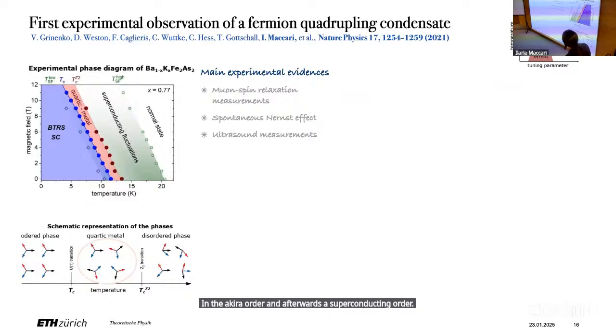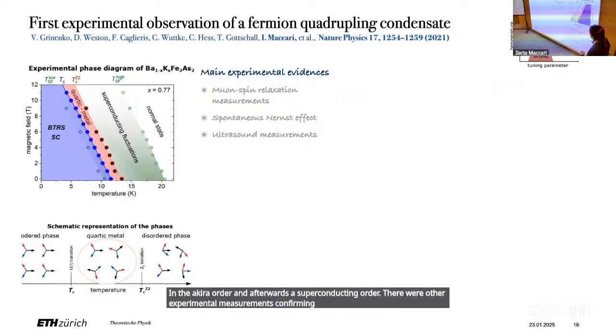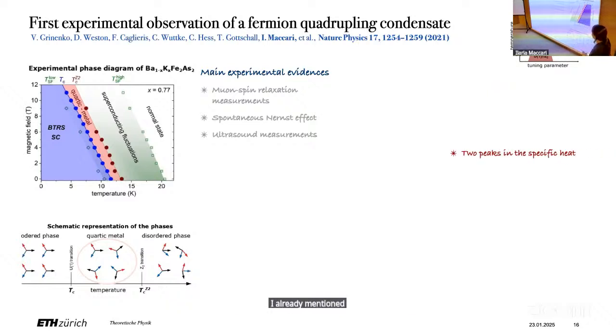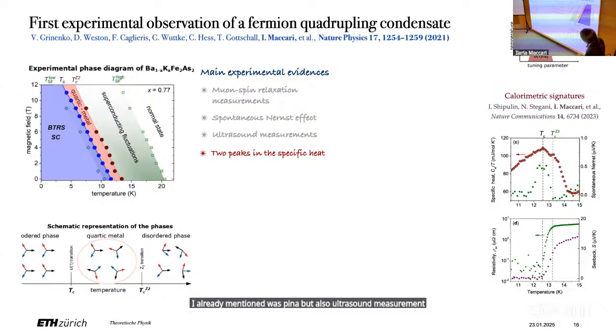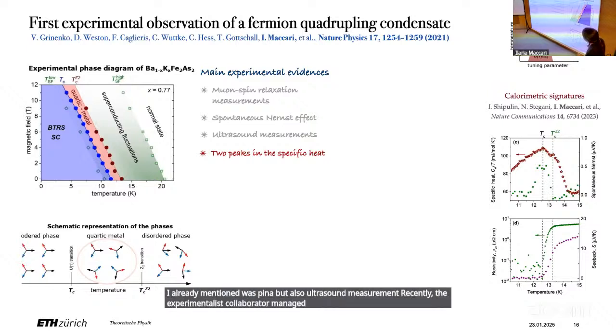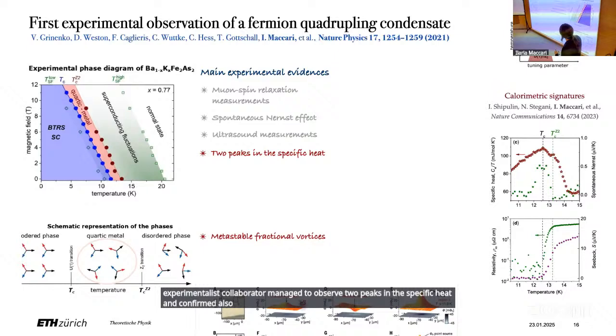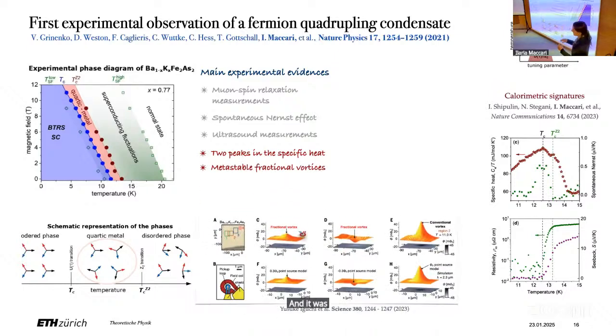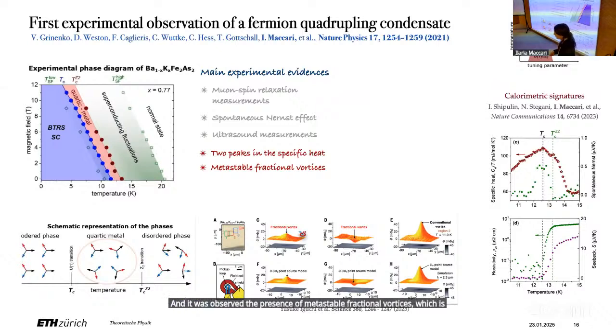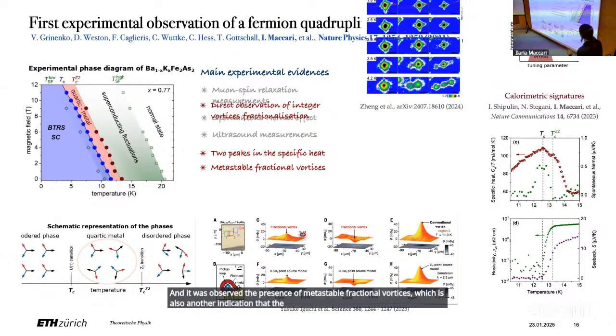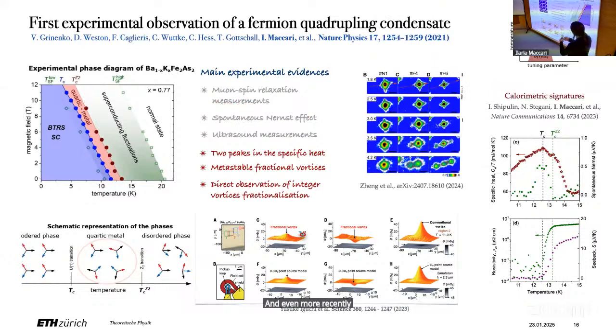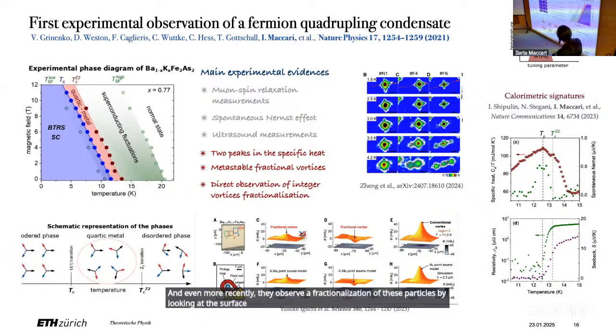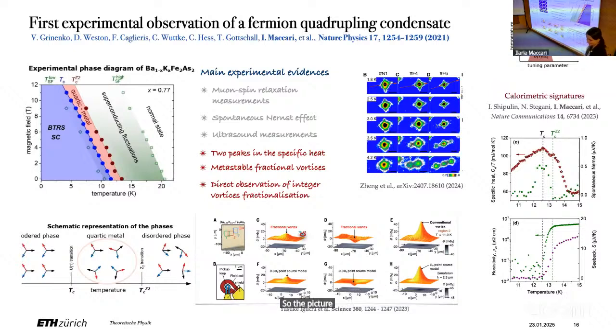There were other experimental measurements confirming these phases. I already mentioned muon spin, but also ultrasound measurements. Recently, the experimental collaborators managed to observe two peaks in the specific heat, confirmed also by my simulations. And the presence of metastable fractional vortices was observed, which is also another indication that the picture seems correct. And even more recently, they observed fractionalization of these vortices by looking at the surface of this material, essentially. So the picture seems consistent overall.